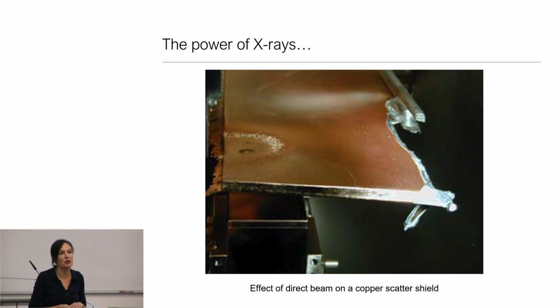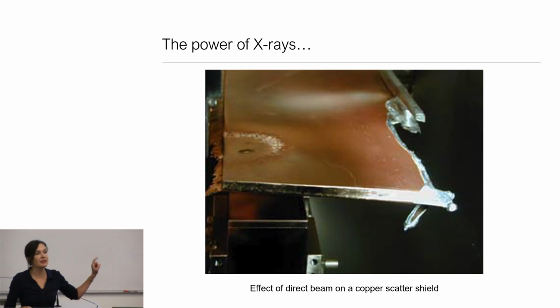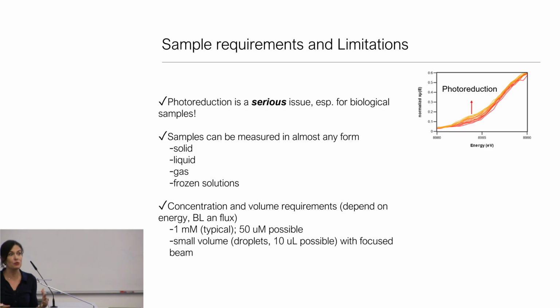Why am I bringing this up? I'm bringing this up because it's something one needs to be very cognizant of when you work with a source that in itself can do that to a piece of copper metal. Now, by the time it gets to your sample, it's been heavily filtered. And this is why my group and I spend a huge amount of time trying to figure out how much flux we can put on the sample, what the dose is, and how long we can afford to scan at each spot.